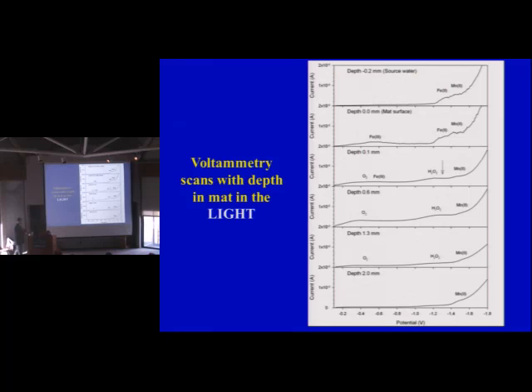So I want to show you what the whole scans look like for voltammetry. So here we are in the source water. Here we are at the mat interface, 0.1, 0.6, 1.3. Here's where your oxygen signal is. We just reversed the way we scanned them in terms of plotting them. Here's your iron-2 and manganese-2, and people say, George, that looks kind of noisy. Yeah, it does when you have it like that. We do blow these up to get better measurements of the currents and the like. But remember, we're doing somewhere from 3 to 5 scans, and we're actually able to give you about 2 to 5% error bars, which is pretty good, 10 at the worst, and this is in flowing water.